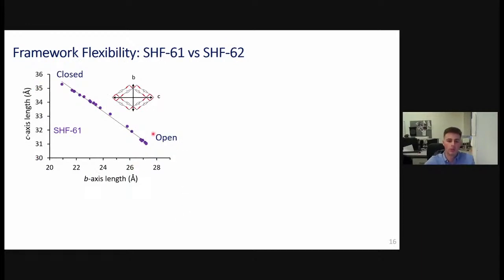So the key question really for us was, what does this modification do to the overall flexibility of the framework? So we go back to our single crystal diffraction mapping study. So we start off looking at our SHF-61 framework in purple here. So we saw this really large change in B and C axis associated with the dimensions of the pore when we go from open to closed.